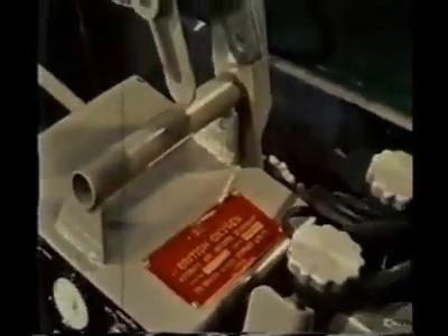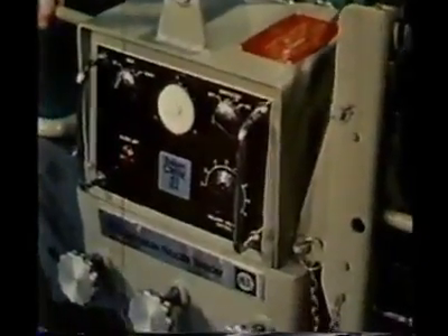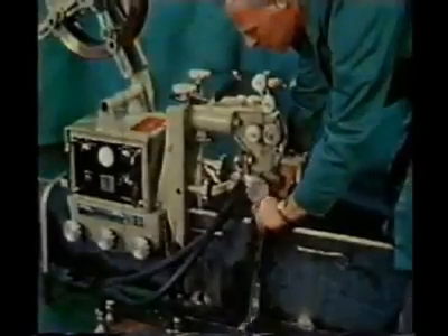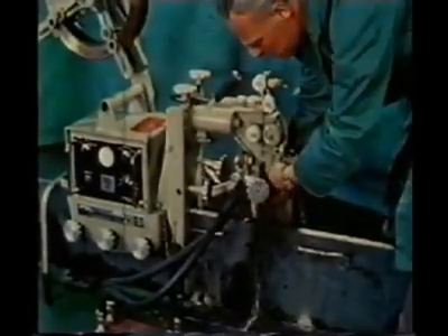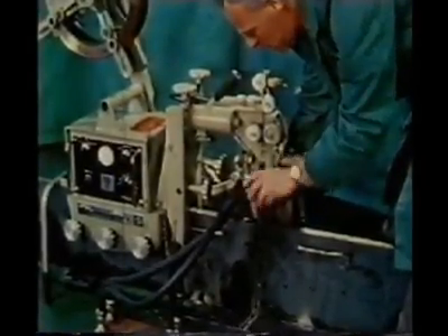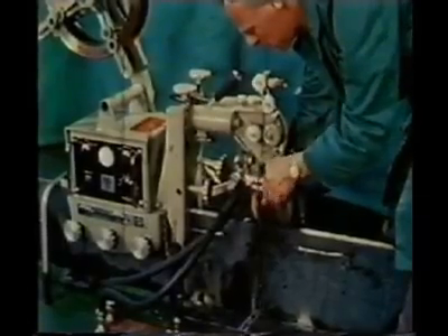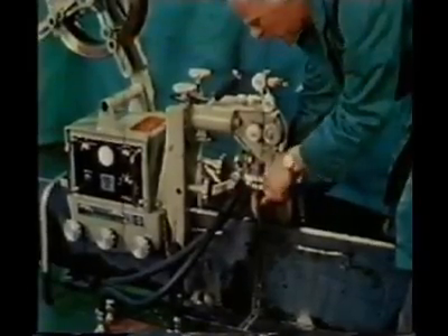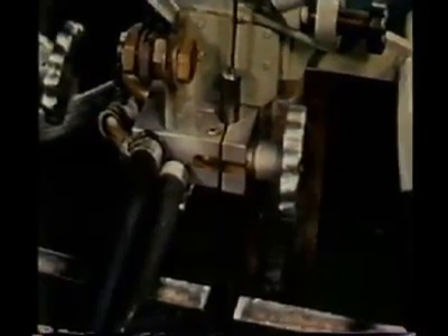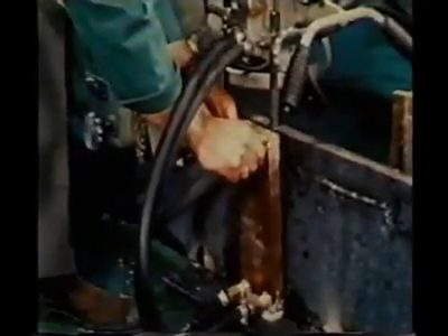And now there's a new development in electro-slag. British Oxygen's simple and portable CN single-wire machine. CN stands for consumable nozzle. This compact, simple and completely portable automatic machine works on exactly the same principle as the larger sub-arc machines, but the mechanism is rather different. To start with, the wire feed is clamped or located at the top of the weld gap and remains there throughout the weld. The complex vertical speed controls of the conventional machine are eliminated.